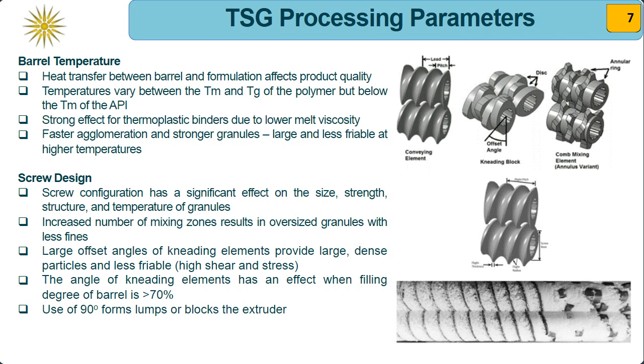Also, the screw design and screw configuration are very important because they have a significant effect on the size, strength, structure, and temperature of the granules. The increased number of mixing zones results in oversized granules with fewer fines, and usually large offset angles of kneading elements provide again larger and denser granules that are less friable. This is mainly because of the high shear and stress that is applied during the granulation process. The angle of the kneading elements has an effect when the filling degree of the barrel is greater than 70%, and it has been found that by using 90-degree elements, we have the creation of lumps or the blocking of the extruder, and hence this should be avoided.